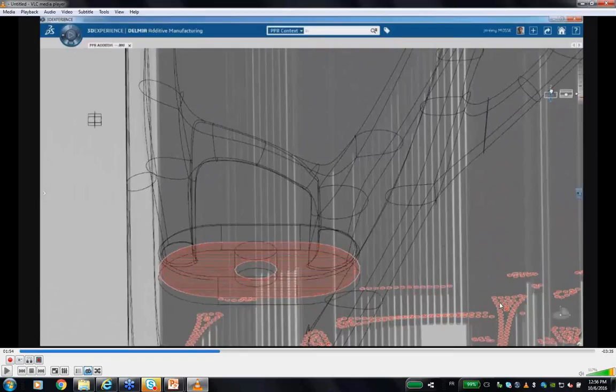We can have a different lasing strategy for the support, because remember, they will be removed anyway at the end, so they might not be as strong as the part itself, even if, especially in metal, the supports not only support overhang areas, they also transfer heat. Like in foundry, when you are making a casting, you try to put the hot spot out of the part, and you create some special geometry outside of the shape that will be removed later on. It's very similar with support. It's heat transfer and of course supporting overhanging areas.